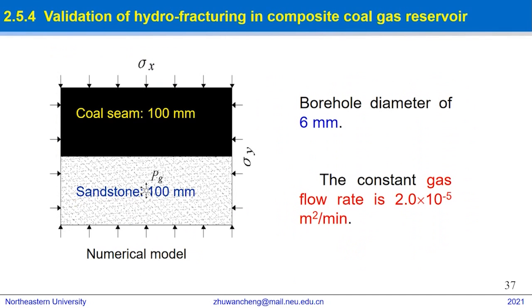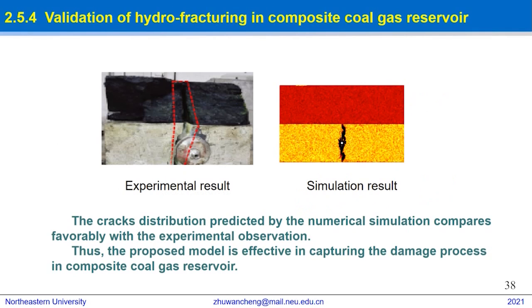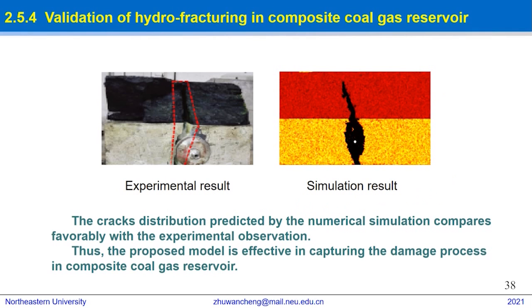This slide shows the validation of hydrofracturing in composite coal reservoir. The numerical specimen is 200 mm in thickness, with a 6 mm diameter hole in the sandstone. The constant gas flow rate is 2.0×10⁻⁵ square meters per minute. The crack distribution predicted by the numerical simulation compares favorably with the experimental observation. Thus, the proposed model is effective in capturing the damage process in composite coal reservoir.